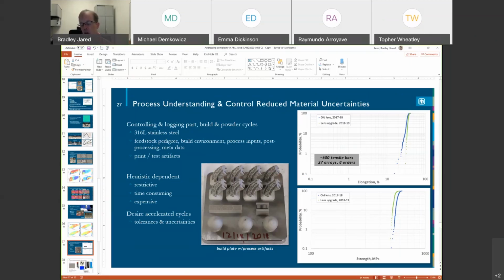These additive materials, certainly in powder-based processes, have a level of variability that is really difficult to get out. And we found that actually this variability within reason doesn't change a whole lot across process settings. At some point, you do cross a sort of a threshold, and it does change a lot. Things like HIP, hot isostatic processing, where you basically heat treat the material with both temperature and high pressure, can produce better material in some alloys, and in some alloys it doesn't help as much. And so those are all things that people look at as well.